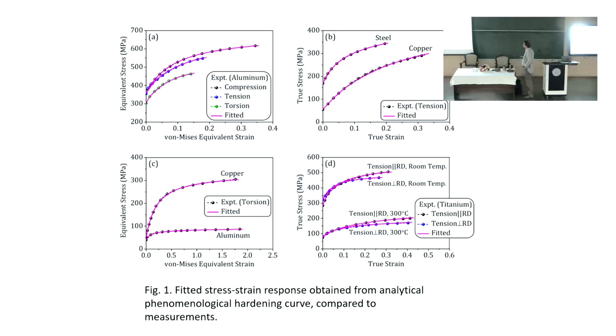And then we can look into titanium, in different directions. So it's a plate, and you can pull it in rolling direction, you can pull it in transverse direction, and then at different temperatures as well, room temperature or 300 degrees C. Each time the fitting is successful.